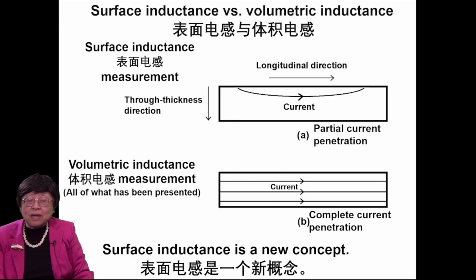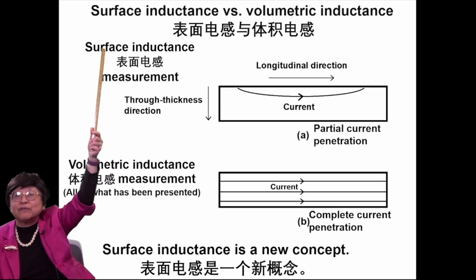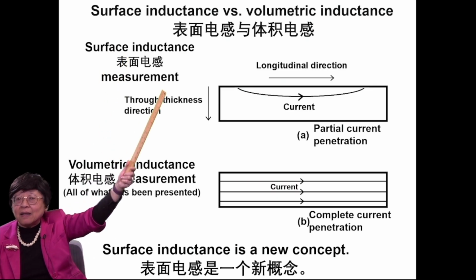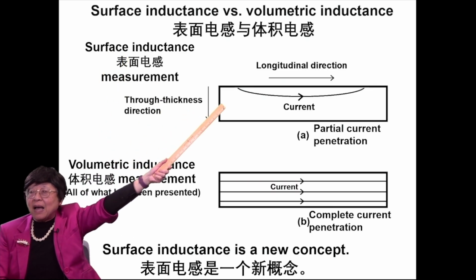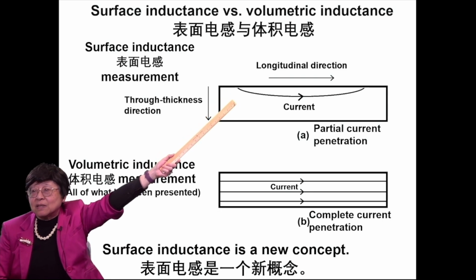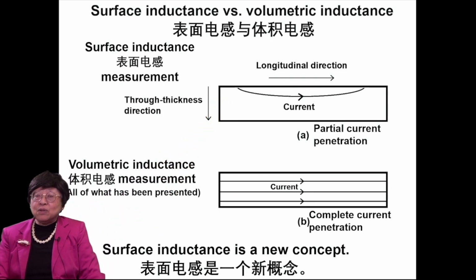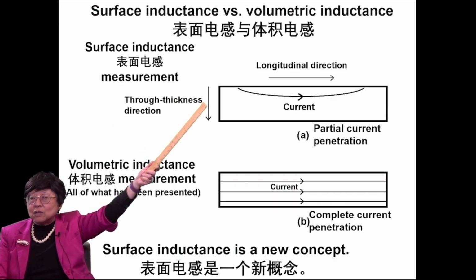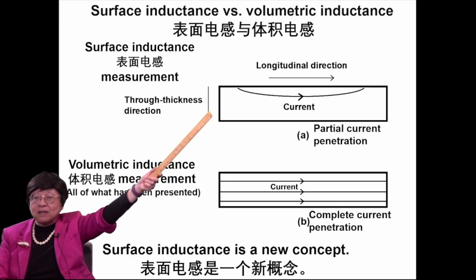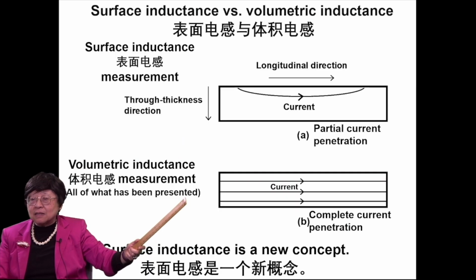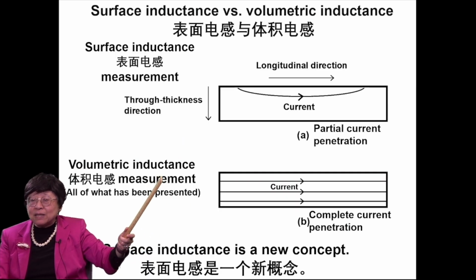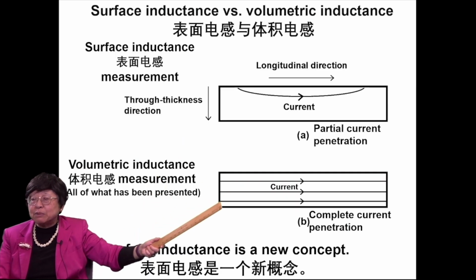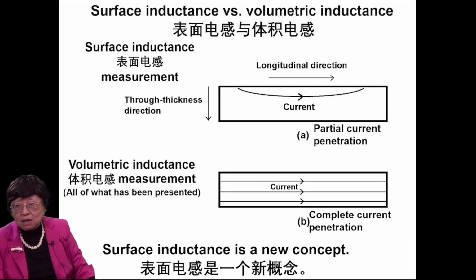Now I introduce a new concept. It's a new scientific quantity, which we call surface inductance. This is obtained by having surface current as injected by using surface electrodes. So we have partial current penetration. That's in contrast to the volumetric inductance, where you have complete current penetration.